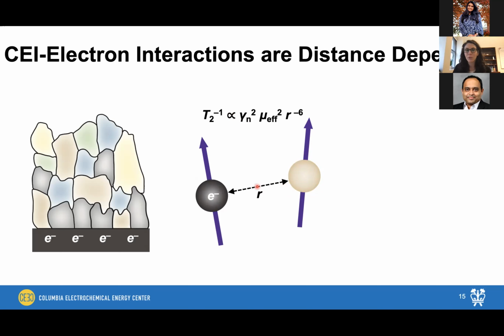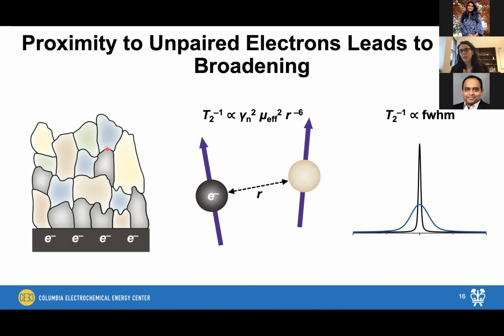So R here represents our inner spin distance between our unpaired electron and our substrate. And this is just a nuclear environment that we're interested in studying in our interface. So things that are very close to our paramagnetic substrate are going to be impacted the most. Things that are very far away in the outer CEI are going to be impacted the least. The reason that we care so much about this T2 parameter is because it's inversely proportional to the full width at half max of our NMR line.